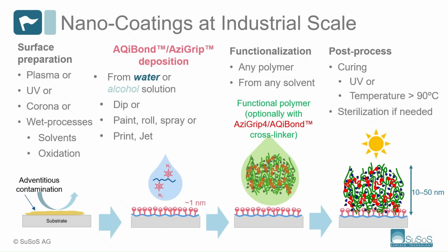So how do we apply AQiBond coating? So we prepare first the surface. We can use plasma treatment, UV, corona, wet processing to get rid of the contamination on the surface. Then we deposit the AQiBond from water or alcohol solution if it's needed by various techniques, be it dipping, painting, rolling, spraying, as we do in the AAA project, printing, jetting, etc. So we deposit the monolayer of the AQiBond that way.